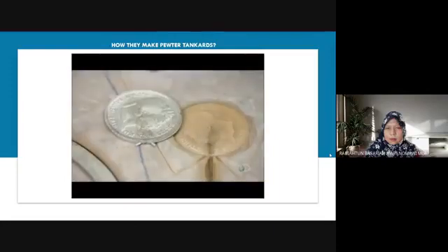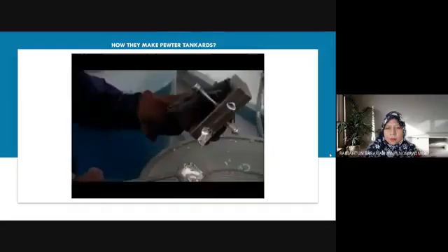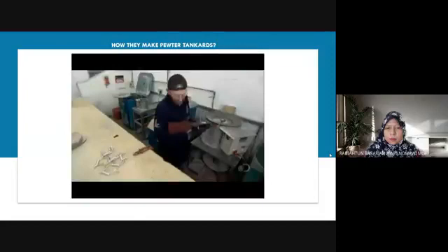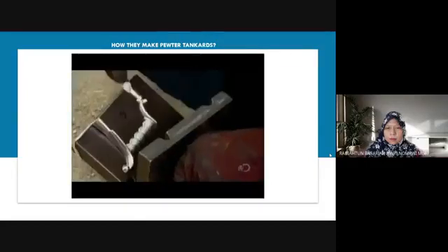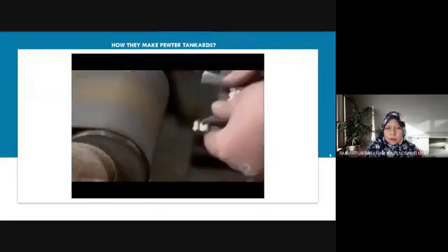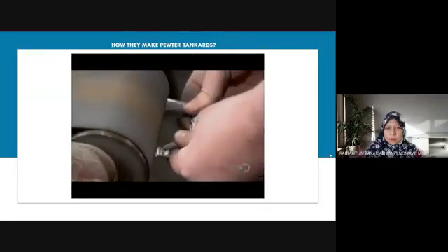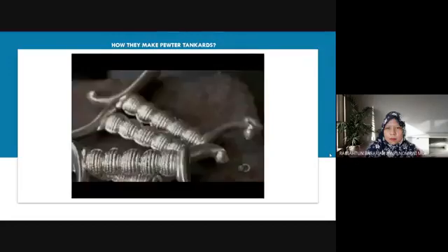To make the tankard's handle, the casters pour molten pewter into a steel mold, then tilt the mold in all directions to spread the rapidly setting metal all along the wall of the cavity. This makes the handle hollow and therefore lightweight. They grind the ends on an abrasive belt so the handle will fit flush against the tankard body.